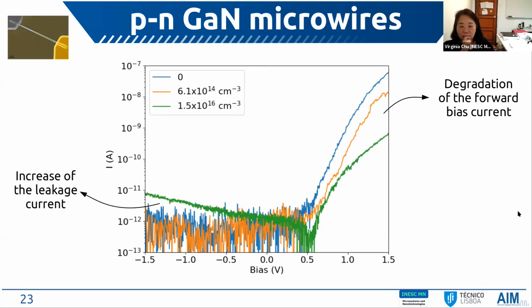Yes. Okay, so in principle, yes, it is. We can do annealing to recover some of the defects created during the irradiation. However, we have not done a lot of studies in this sense yet, so this is still work that is ongoing. But we have observed that for the n-type gallium nitride samples, we were not able to completely recover the electrical properties, but we were able to recover them to a certain amount. We are not sure if in this case, for example, the leakage current is going to be reduced after annealing, but we do surely expect that part of the forward bias current can be recovered.